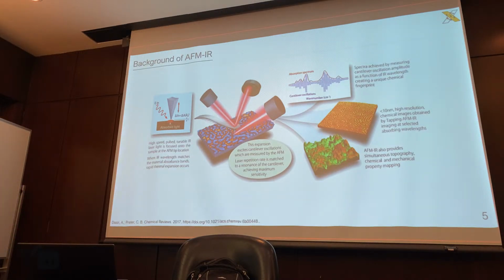Now, I know a lot of you have just gone through this exact same slide probably 24 times already, but I'm sure when I'm gone, somebody will take over for me, so I think it's good to go over this little bit of background. One way people have bypassed the diffraction of light is using AFMIR, which uses this photothermal effect, where we can shine our material, which can be a material blend, it can be a composite, really any material, but it must be excited with a particular wavelength of light that corresponds to the excitation or resonant frequency of your molecule. So when we shine in a laser, and it's a monochromatic laser, of course, when it absorbs light at that particular wavelength, we create a rapid thermal excitation, which is then detected by this cantilever probe.